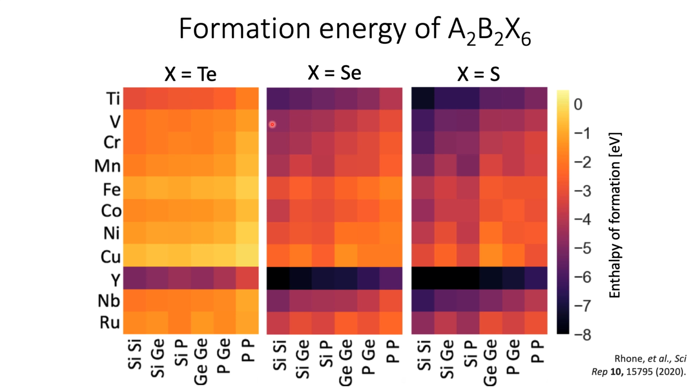Again, the A site substitutions are on the vertical axis, B site on the horizontal axis, and the different X sites in different panels. Now the color here represents formation energy, with a more negative value for formation energy being more chemically stable. You notice that there's a pattern going from left to right in the first row of the transition metals, and left to right in the second row, of decreasing chemical stability, and increasing chemical stability going from tellurium to sulfur up row 6 of the periodic table. And again, we want to exploit patterns in these data with machine learning for quantitative predictions.